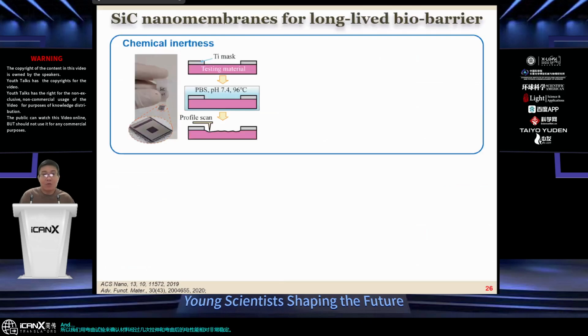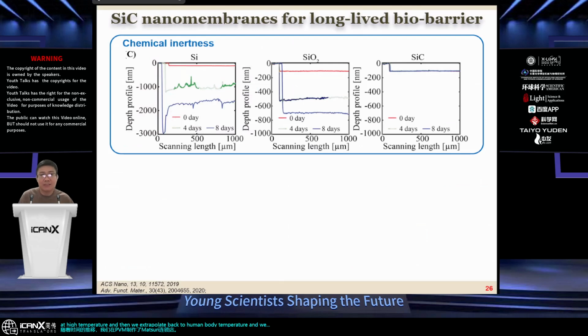And for long-term implants, we want to see how long the material can withstand biofluid. So one way that allows us to accelerate the test is the hydrolysis reaction. We measure the material change over time in PBS at high temperature, and then we extrapolate back to human body temperature. And we also benchmark with other materials like silicon and silicon oxide. For silicon, about 2 or 3 micrometers was removed after 8 days in PBS. For silicon oxide, about 600 nanometers was removed after 8 days. For silicon carbide, after 8 days at 96 degrees C, the thickness remained constant.